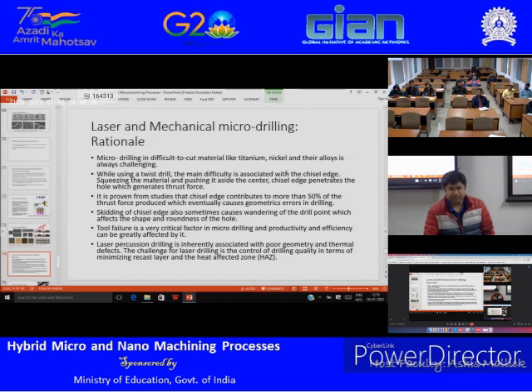It will significantly reduce the machining time, because with laser, it will take just a fraction of a second to make that hole, and then when you are using milling, the hole is already there. So it will take comparatively less machining time, and it will significantly reduce the heat affected zone and recast layer, right? And also it will improve the profile accuracy, because laser usually doesn't give good profile accuracy. Mechanical machining like micro machining, micro turning, milling or drilling gives very good profile accuracy.